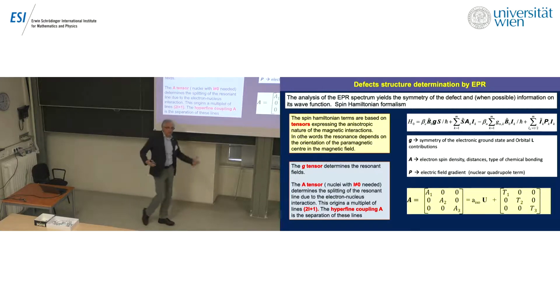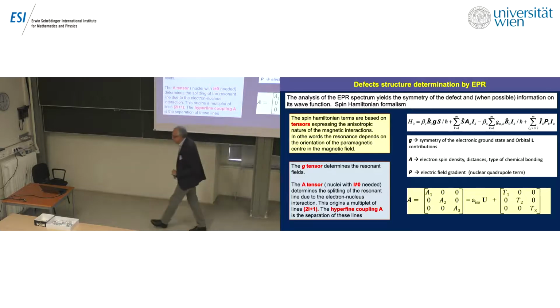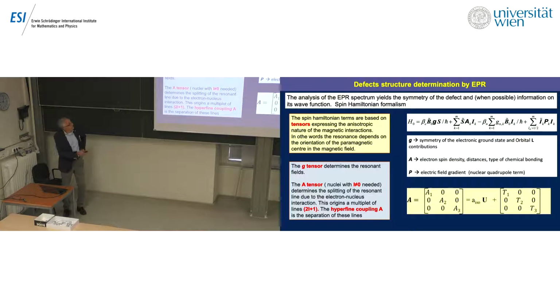EPR is a magnetic resonance technique, and the formalism used in this technique is the spin Hamiltonian, and the main elements of the spin Hamiltonian are governed by matrices that are tensors. The g tensor and the A tensor are the more important for what I'm going to say today. g depends on the symmetry of the electronic ground state, on orbital admixture, and on the contribution of the orbital momentum. A is the hyperfine matrix, and it determines the interaction between the electron spin and the nuclear spins that are in the surroundings. This is expressed in terms of two different contributions: the Fermi contact term related to s orbitals, and the dipolar terms that hold for p and d orbitals.